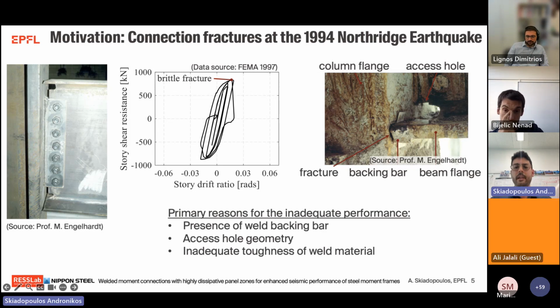The primary reasons behind the inadequate performance of the connections at that time are the presence of the weld backing bar that was associated with the notch condition that increased the fracture potential in the critical beam flange to column face connection, the weld access hole geometry that was concentrating stress and increased stress and strain demands at that region, and finally the inadequate toughness of the weld material that was utilized at that time. For all these reasons, inelastic panel zone design is not promoted in current design norms.